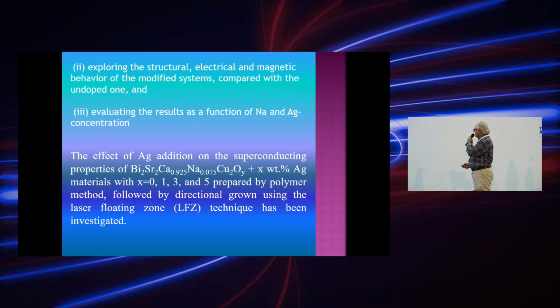As I explained, we have found the best condition for sodium inclusion, 0.075, and we fixed this as the main matrix, and we have added 0, 1, 3 and 5% of silver in order to see the variation of the structure.